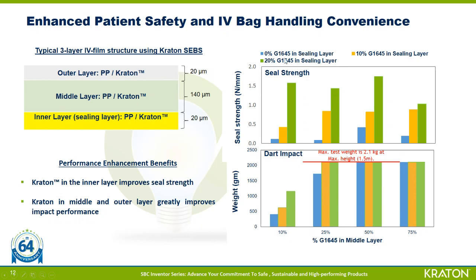We studied the effect of varying the amount of G1645 in the inner sealing layer, as well as in the middle layer, on 2 properties that we have shown you here, such as the seal strength and the drop dart impact resistance. In both these data sets shown here, the amount of G1645 in the sealing layer was varied between 0%, 10%, and 20%. And they are shown by the blue bars, yellow bars, and the green bars respectively. And for both of these graphs, you can also see the G1645 in the middle layer is shown as the x-axis, where the amount of the polymer in the middle layer was varied from 10 to 75%.